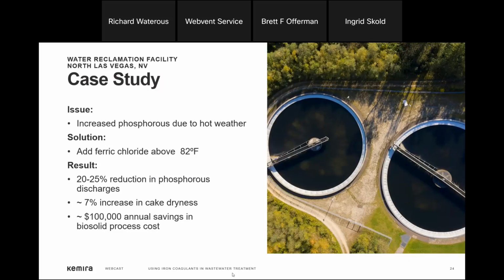The solutions: studies conducted at the North Las Vegas facility showed an increase in phosphorus levels when water temperatures exceeded 82 degrees Fahrenheit. Ferric chloride was introduced to chemically remove phosphorus compounds by adding 200 to 400 gallons per day from March through October. The result: improved water quality, phosphorus discharge limit compliance, improved biosolids production, and biosolids process cost savings.